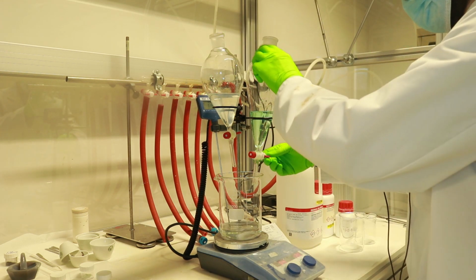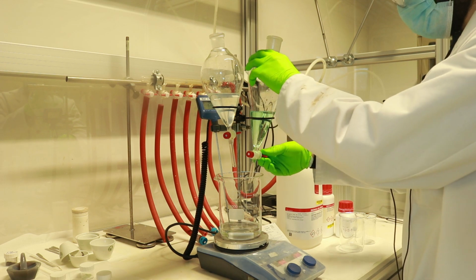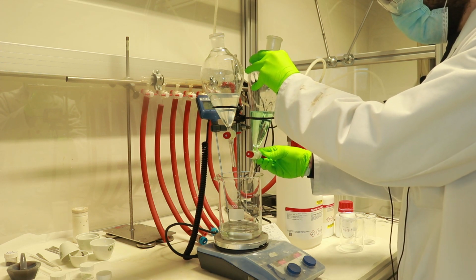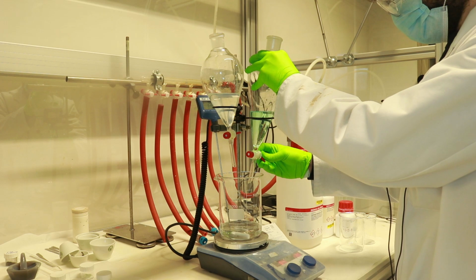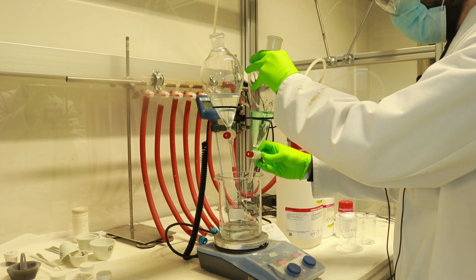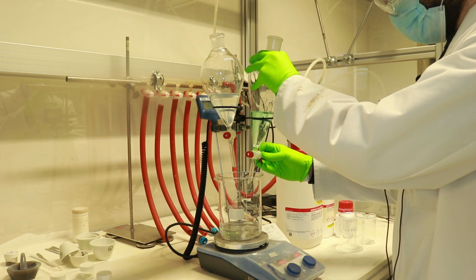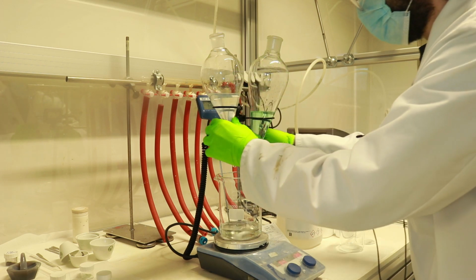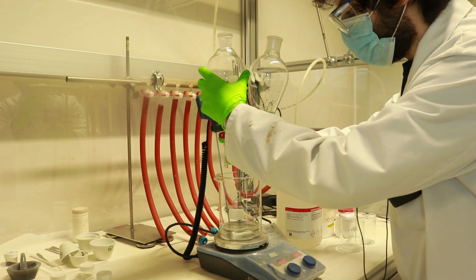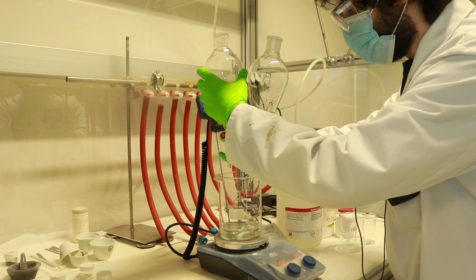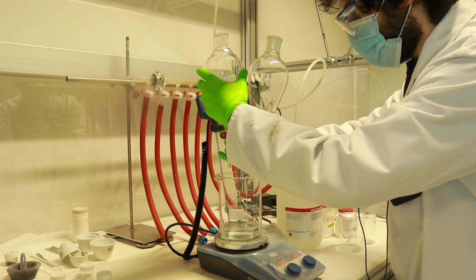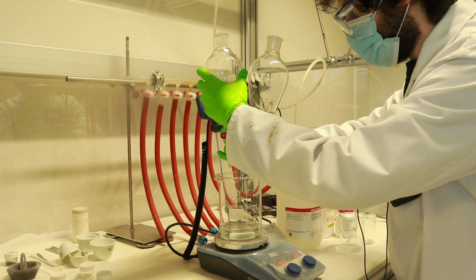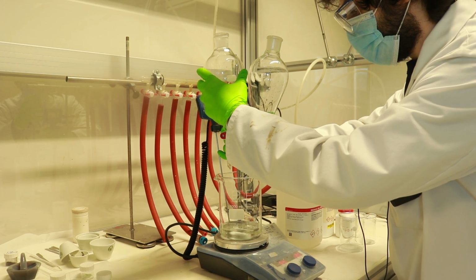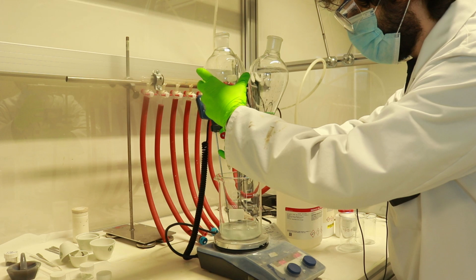Now that everything is ready, I will start to drop both solutions into the beaker. And the rates of addition need to be controlled so that the pH is higher than 7. In this case, we are aiming for a pH of 9 for the precipitation.